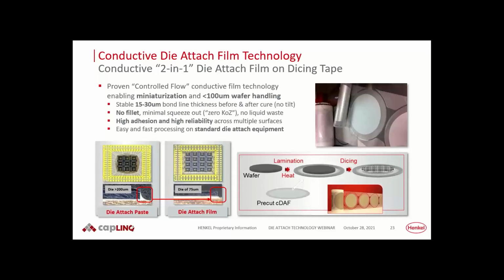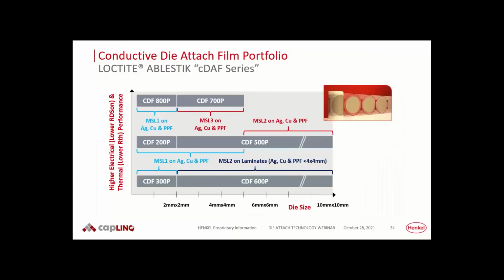And I think here what is important, these die attach films, these are the conductive ones in this case, are supplied on a dicing foil. So basically, normally you would laminate your wafer on a dicing foil for dicing and pickup. Here, you laminate the wafer on the silver layer, then you do the dicing, and then you pick up the die with the very controlled 15 micron silver layer die attach already on it, so no need for dispensing anymore. So here we have a nice product portfolio.